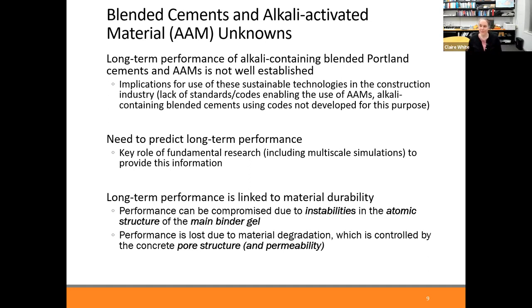There are other ions as well that degrade concrete, such as chloride and sulfates. And what they do is they permeate through the pore structure of the concrete. And then they can cause phases to dissolve, or they can cause rusting of the steel, as another example. So the pore structure of concrete is very important.